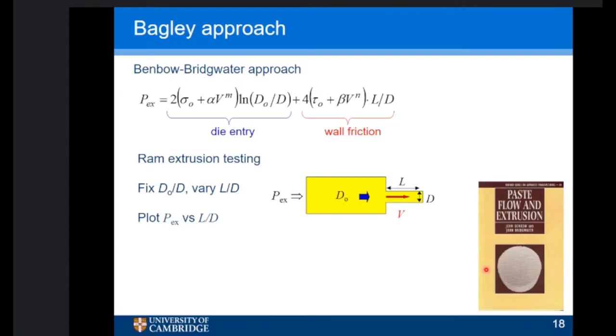So what John Benbow and John Bridgewater did in looking at paste was say, well, let's take a very simple approach, treat it like a simple engineering plastic. So we'll extrude something by ram extrusion, and we'll measure the extrusion pressure Px from a barrel diameter of D0, a die land diameter of D, of length L at a given velocity, and we'll just relate the extrusion pressure to a term dominated by die entry, that's the extensional flow in the die entry, which was related to the change in area, so the log D0 over D, and then something to do with the paste yield strength. And that's what these terms here are.